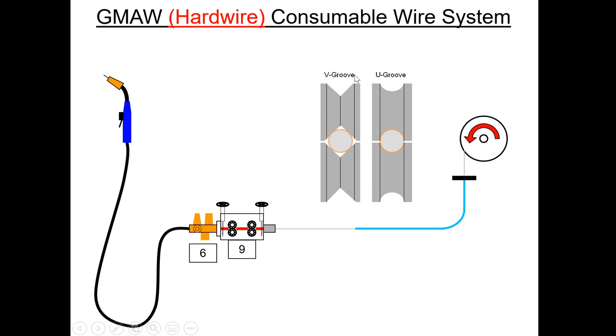One of the things we're dealing with here are these drive rolls. There are different types of drive rolls for different types of equipment. The normal equipment you'll see for steel is a V groove. If you were going to go to a more high-end machine, for example a Fronius, you might have a U groove drive roll that puts even pressure on the electrode and tries to reduce the forces you would get from just having 2 points of contact from your standard. That being said, the Fronius equipment usually outperforms other equipment as a result of a number of different things, which most agree has to do with keeping the wire as intact as possible. And this certainly would keep our wire intact as possible.